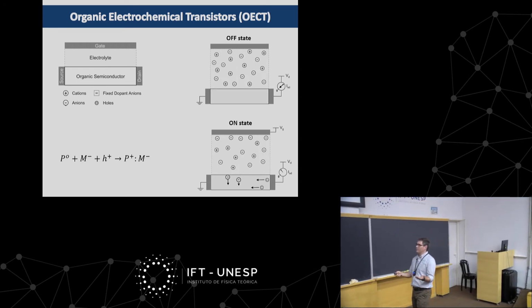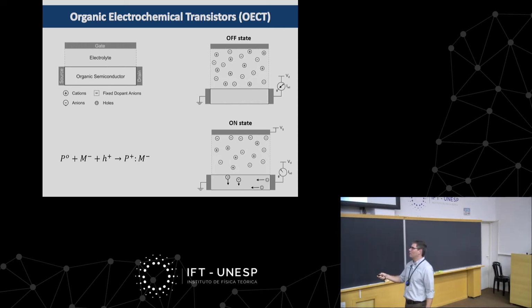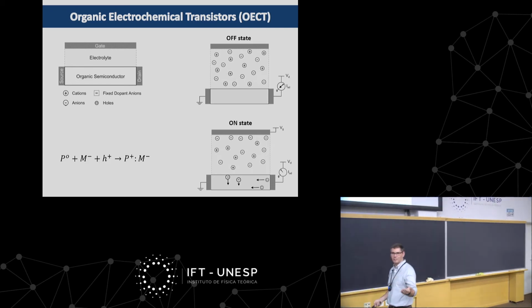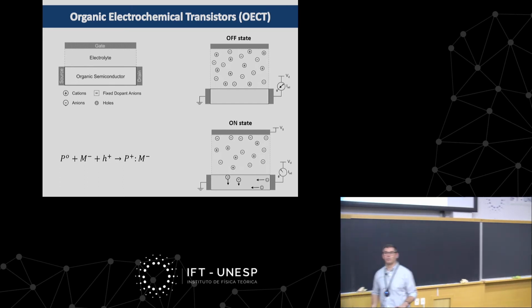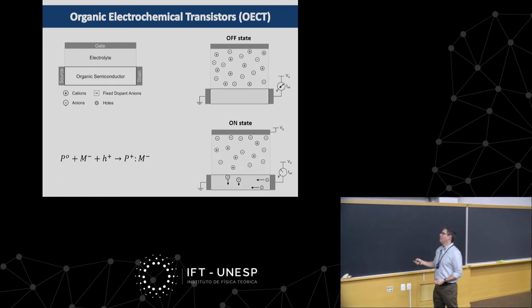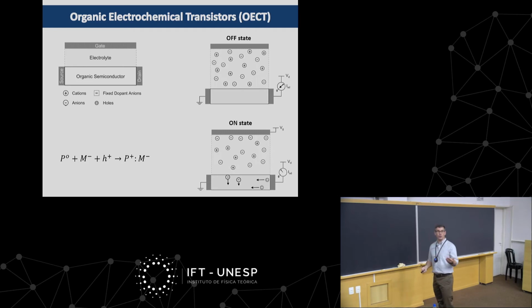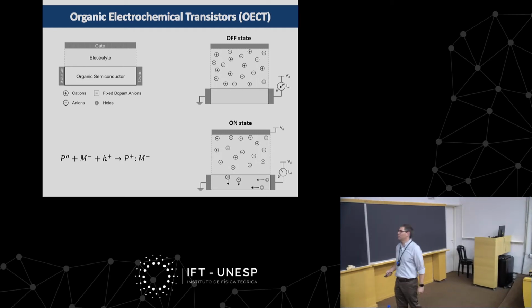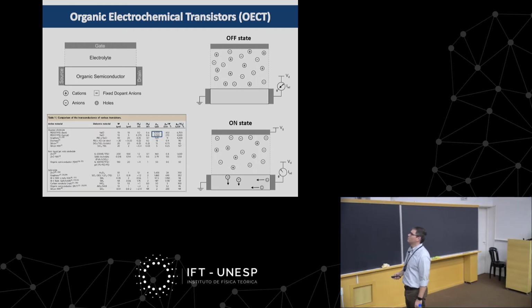And basically this is an electrochemical reaction that happens. So you have a neutral polymer plus a negative ion plus a hole, which is injected. And then you create a polymer that is positively charged, and that is bound to that particular negative ion. So this is some sort of electrochemical reaction that is going on because of the interaction between the polymer and the ionic species.